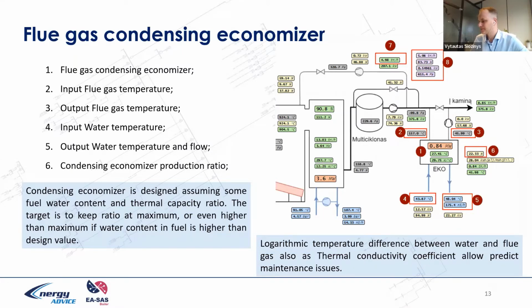It's very important to monitor the ratio of the flue gas condensing economizer's production with the boiler production ratio, because the condensing economizer is designed assuming some fuel water content and thermal capacity ratio. The target is to keep the ratio at the maximum or even higher than the maximum if the water content in the fuel is higher than the designed value. So if we have a target of 22-23% ratio and less capacity, and if we have a higher water rate in the fuel, probably we can reach a higher rate of heat production